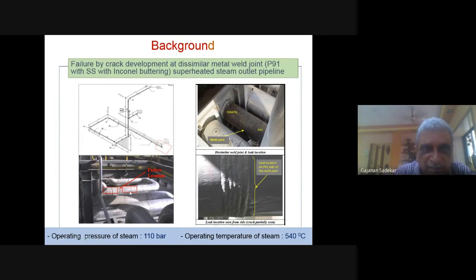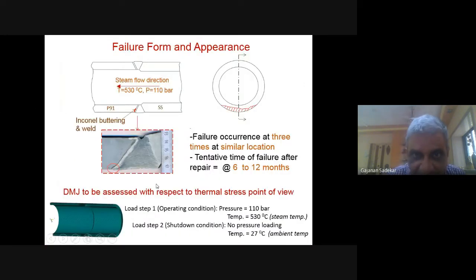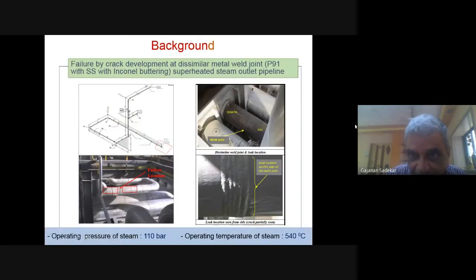So here what you see is nothing but we collected all the data on the piping to see what type of support of the piping, what type of constraints are coming on the piping, because the problem reported was that every 9 months they used to get a crack on this weld and they were required to change the pipeline. Okay, so this joint, which I'm going to show you in detail in the next one. Here, can you see this joint? This is the dissimilar joint. This is a P91. This is a stainless steel, and this is the joint. So this joint is the failure location.